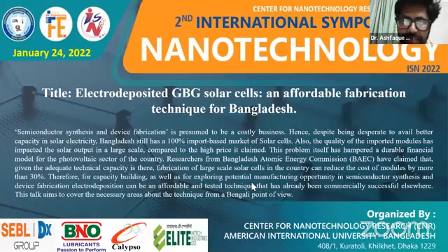Excellent questions. The first question is about reproducibility. And I absolutely agree with the person who's asking that reproducibility can be a matter of concern for us in the lab as well. But like I told you, it has been industrially tested by BP, and BP has commercially produced 11%, 12% efficient modules using the electrodeposition technique. In our lab, we have found that we can reproduce 15%, 14% efficient cells in lab-based